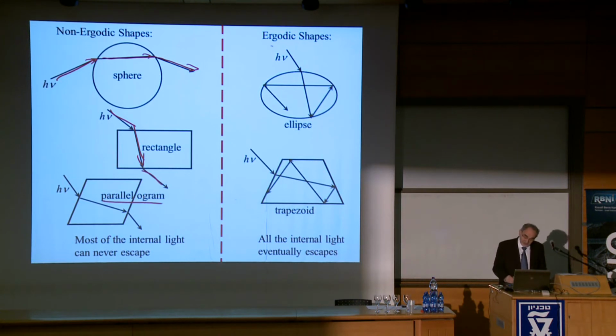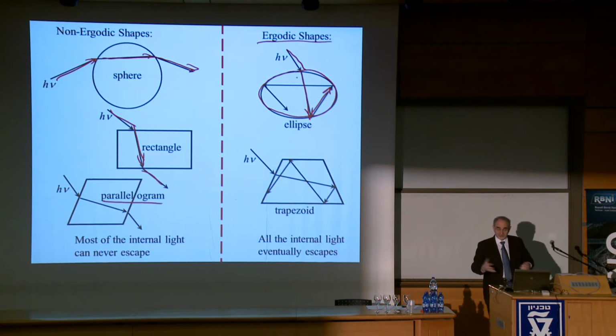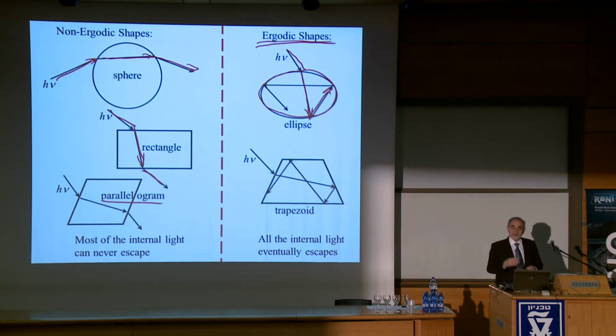Now, this is to be contrasted with the ergodic shapes. And so we have a shape of an ellipse. An ellipse is qualitatively different from a circle or a sphere. The reason is that the light comes in, and it starts bouncing at strange angles, and after a few bounces, it explores all the possible internal angles. In statistical mechanics we would say it explores the full internal phase space. So for ergodic shapes, the time average is the same as the phase space average. That's the meaning of ergodic. It means with time, you will eventually explore all angles. The trapezoid, another shape, well, it's an odd shape, but the angles bounce and bounce, and the light ray forgets the original angle and fills all the internal angles.